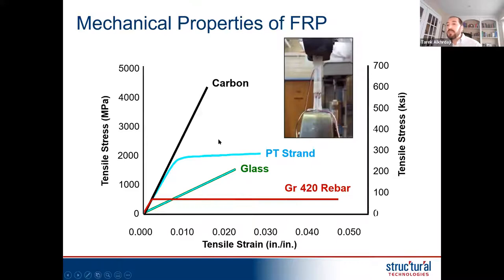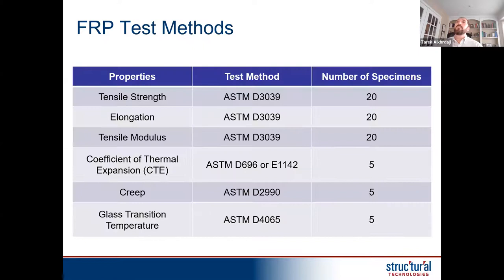So they don't have this yield behavior, which means that's going to change how I calculate some of the strength of the material. Glass is much lower strength than carbon, maybe 1.5 to 2 times stronger than steel, but the stiffness is almost 1/3 that of steel. That's why, because of the high strength and high stiffness, the majority of strengthening applications are done with carbon. Glass is more used for masonry and brick or for some protection.